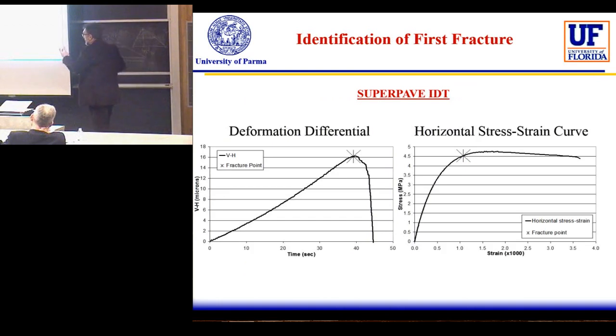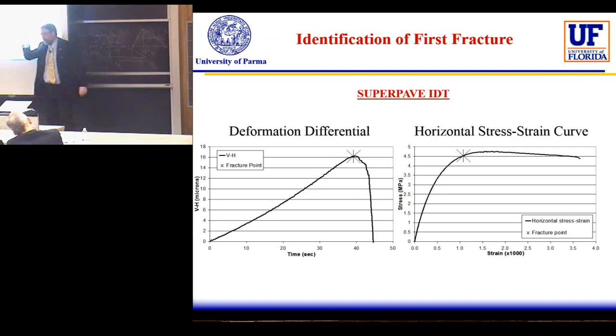The last topic: how was it possible to define the point where the first crack appeared? At that time, the DIC method was still not developed, and at UF they defined a way to identify the point of the first crack using this definition of deformation differential, that is the difference between vertical and horizontal deformation, and the peak of this curve is considered the point where the first crack appears. That is before the peak of the stress and strain curve, because the material is considered failed when the first crack appears.